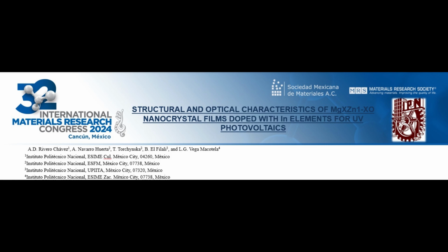By forming magnesium alloys with varying magnesium content, larger bandgap windows can be created for ZnO-based devices. The bandgap of these alloys shifts towards the visible to ultraviolet range depending on the magnesium content. Increasing the magnesium content in MgZnO films within the range of 0 to 20 atomic percent enhances transmittance in the ultraviolet range for 3.37 to 4.0 electron volts at 300 kelvins, while maintaining the crystalline structure. This tunability of optical bandgap in MgZnO films makes them ideal for ultraviolet optoelectronic devices.